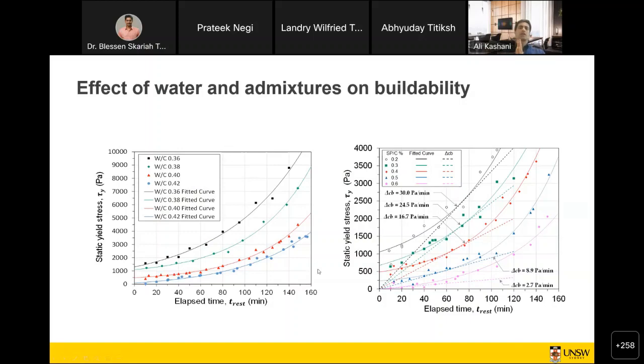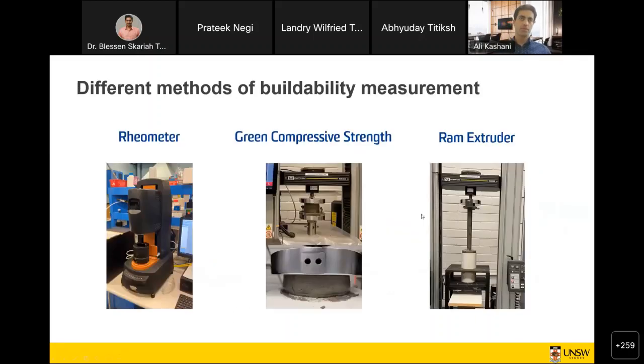So based on those, we can change the material and mix design, for example, changing the water to cement ratio, changing the superplasticizers, and see if we are within those criteria, or if we are just crossing the buildability limit or other limits of 3D printing. But one of the things that we have found out is that using the rheometer as a tool to assess that is not really comprehensible, because some of those 3D printing mixes are very viscous. Because of that, some of the rheometers are not going to be able to test those very stiff materials, and the result might have a lot of errors even if they do. So we need some other tools.